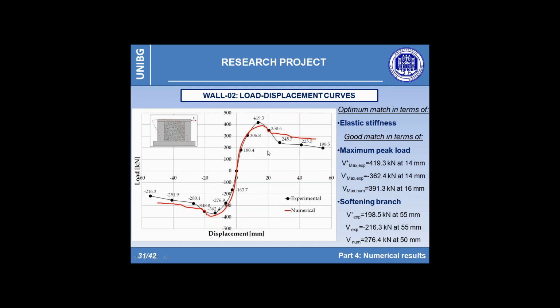Speaking about the structural behavior observed for the specimen wall 2, the same graph of load versus displacement, also proposed previously, is now shown. In this case, the prediction is less performing. Nevertheless, the results are quite satisfactory. In fact, the numerical curve appears to be consistent and quite similar to the envelope one, in particular concerning the stiffness during the elastic phase.